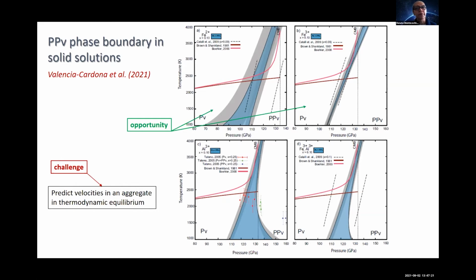So here is a very interesting result: ferric iron and ferrous iron have very different effects on the post-perovskite transition. And this was clearly observed by Catalli and Shim and collaborators. And it's quite rewarding for us to see that the narrow region observed experimentally is clearly reproduced computationally. So there is an opportunity that if we investigate the nature of these discontinuities in the D double prime, we might be able to identify regions that are ferric or ferrous iron rich. For example, according to these calculations, a double crossing of the post-perovskite boundary is almost impossible in ferrous iron rich bridgmanite, but it's clear it can happen in ferric iron rich bridgmanite.